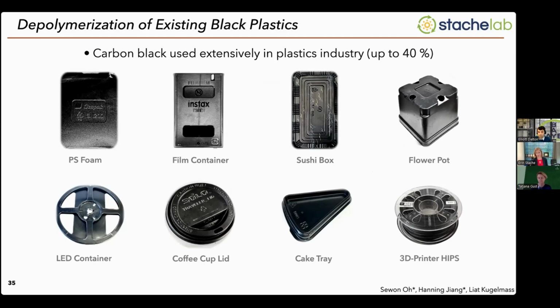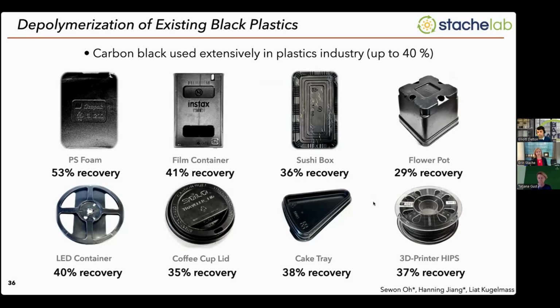All we did was cut them up to put them in a vial so we could irradiate them with visible light. No other carbon black was added. No other catalysts were added. It's just the plastic that the plastic manufacturers produced, got used, and then we found and put into our system. And in all cases, we're able to generate styrene monomer from these existing black plastics. So the additives that plastics manufacturers are putting into these black plastics can induce their depolymerization with pretty high efficiencies.